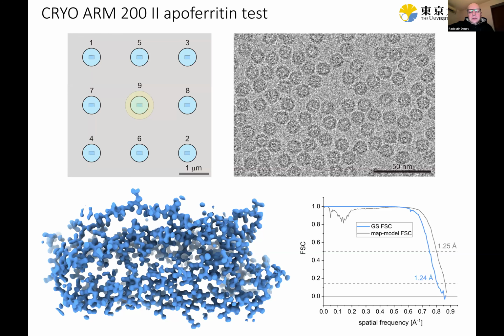The difficulty was practical. I've never used a microscope in this range, and you have to calibrate. We use cryo-EM software to automate the experiment. With these high magnifications, you don't see much on the fluorescent screen, and doing all the calibrations was challenging. There was also something related to the microscope configuration itself, because switching between mag ranges, the lenses work in a particular optical configuration up to certain magnifications. Going to the higher range, the strongly excited and not so strongly excited lenses switch configuration, and there is a big shift between these ranges.